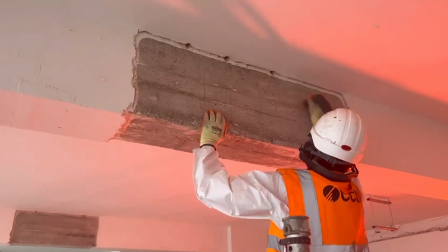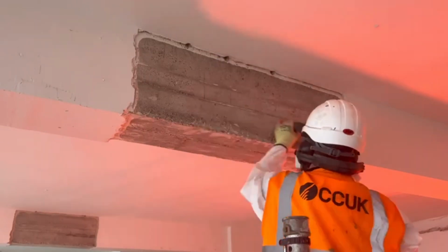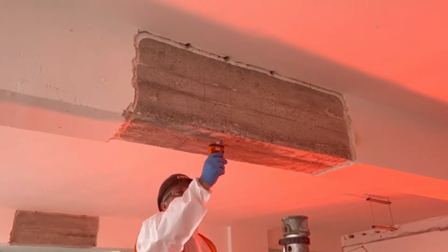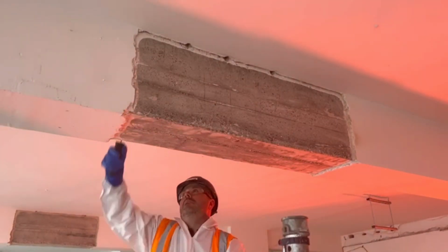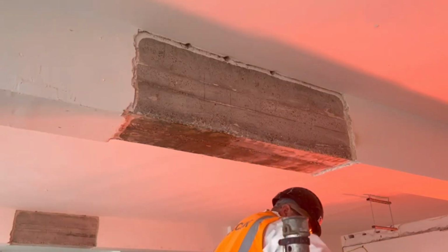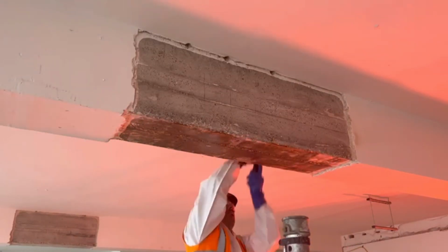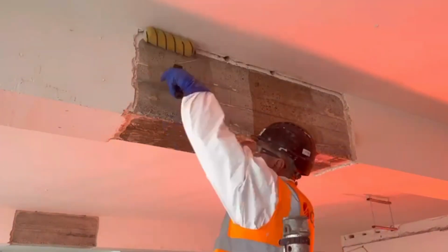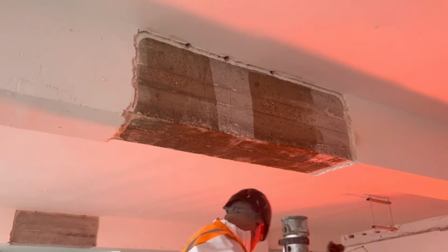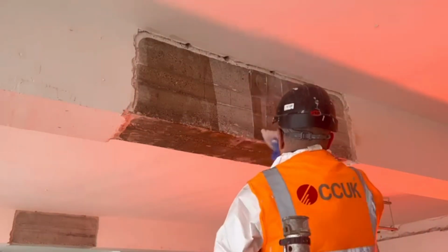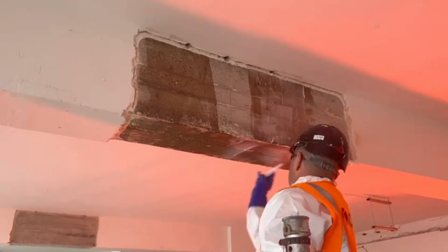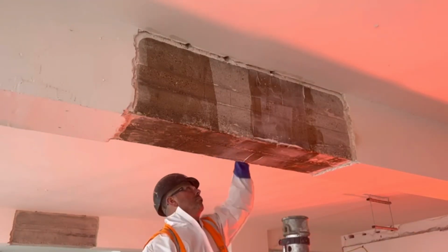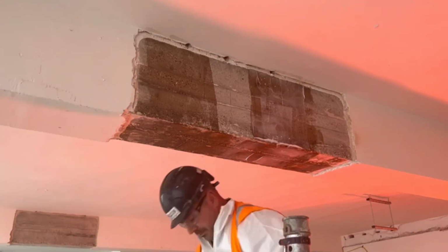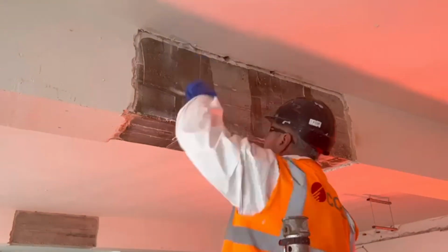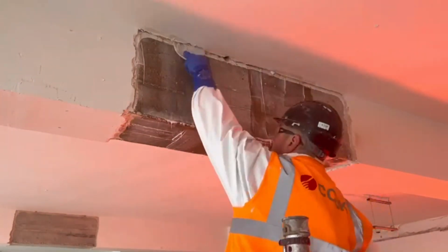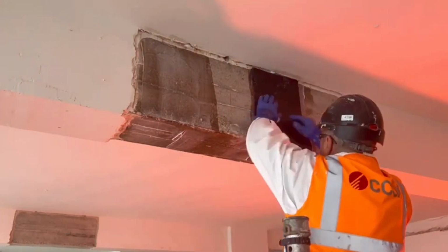So before doing the application, they will take the temperature readings again to make sure that the temperature is still as it needs to be after putting the heating there in this particular instance. After that, they'll do priming, which is done using pure epoxy, so it can soak into the concrete. Then they provide the first coat of thickened epoxy, which is the white color epoxy we are seeing. And then once that coat is applied, they will unroll the first layer of carbon fibre, which is saturated on the site in a different area. So when they are applying it, it's in wet condition.